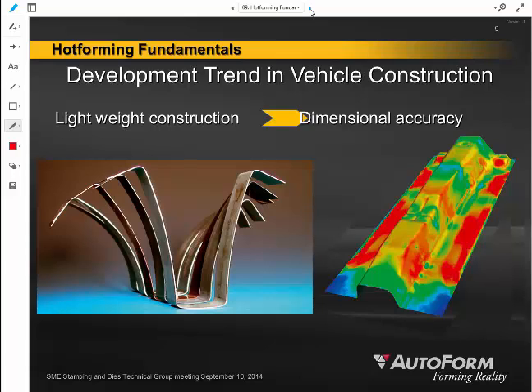Other challenges raised by trying to go to these advanced high-strength materials and increased strength materials: not only are stronger materials typically more difficult to form, right? They have lower forming limits or formability limits, but they also tend to have greater amounts of spring back. Right? So as we've tried to introduce these lightweight vehicle constructions, whether it's high-strength steel or aluminum, in both we do see a greater amount of overall spring back. And that makes it very difficult for us to achieve our dimensional accuracy goals, our PPAP goals. Right? It doesn't matter if I can make the part, if I can't make it dimensionally accurate to the right size and shape and tolerance, that new strong component or lightweight component doesn't do me any good. So these are the challenges that we're using hot stamping and hot forming to try to address.